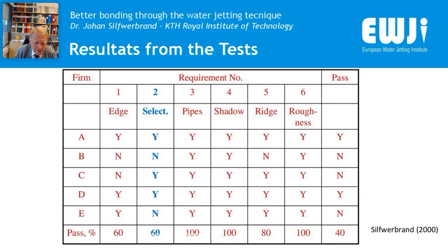And here is a summary of tests from 5 different companies with 5 different equipments. And I call them just A, B, C, D, and E. And you can see that we didn't just look at selectivity. We looked also at other types of results. But here I'm concentrating on selectivity. And you can see that the equipment A, C, and D were able to work selectively.